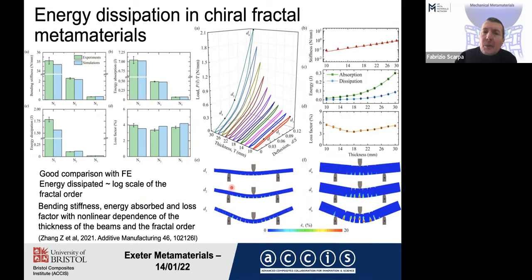And the bending stiffness, the energy absorbed, and the loss factor all have a sort of nonlinear dependence with the thickness of the beams. And the loss factors, especially for very thick fractal beams, look like they have a sort of minimum and then stabilize. And this is due to the fact that some of the features given by the fractal order in terms of contact friction between the vertical walls need also to be balanced by the viscoelasticity of the core material itself. So you need to be careful when you select the material to make this kind of architected metamaterials in terms of energy dissipation, because you also need to consider every type of micromechanism existing at the material level interacting with the architecture itself.